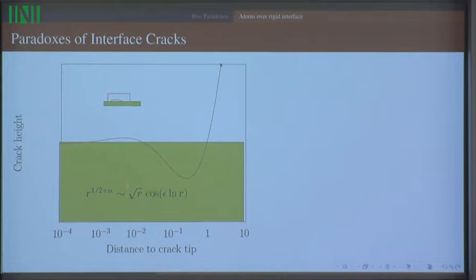For ordinary fracture mechanics, where the two solids in contact are identical, there's a generic continuum singularity that builds up at the tip of any crack, where the opening displacement goes as distance to the crack tip, r to the 1/2 power. It's a square root. But if the two solids are different and have different elastic moduli, then there is a complex correction, and so the solution is supposed to oscillate near the tip. And so it takes this form.